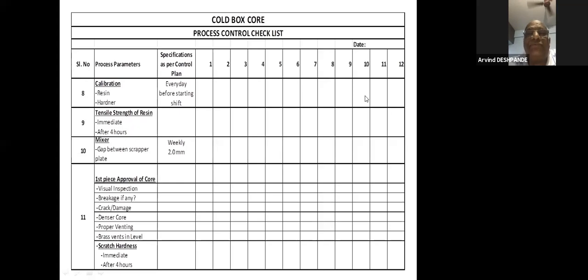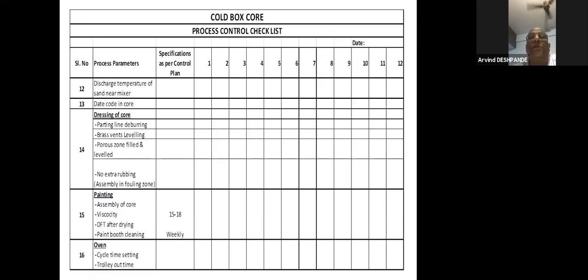Then brass vent. Normally the brass vent doesn't come level. If it is not level, that has to be taken care of while dressing. Then scratch hardness, immediately and after 4 hours. Scratch hardness is basically the most important test. Atom-wise at start or frequency is to be decided by each foundry. But this is the most important test, at least nowadays when monsoon is there. Everybody knows that core sand is hygroscopic. So these tests are most important and should be within limit as per the control plan. If it is not falling in the limit, accordingly we have to do corrections.